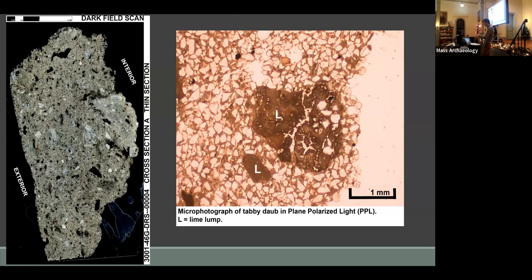So sand along with crushed oyster shells are added to lime as aggregate, which offsets the shrinking and cracking of the lime as it dries, which provides strength, workability, and durability in the material. Now, sand and oyster shell are both inert aggregates, which means that they do not chemically react with the lime binder. And the sand aggregate is overwhelmingly quartz and has subangular to subrounded morphologies, which suggests that the sand came from a river in origin, which is not too surprising considering Old Fort Plantation is directly along the Beaufort River, but it does contradict historical recommendations for pit sand and a preference for salt-free materials in tabby production.